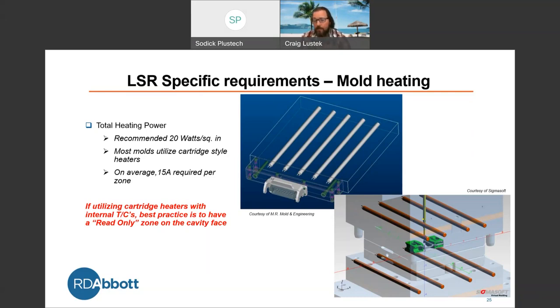A lot of the newer heaters out there, something to watch for, they have internal thermocouples, which are nice, but as soon as you turn the mold heaters on, within anywhere from 5 to 15 minutes, it'll tell you your mold's up to temp. I always like to have a read-only zone added in the face. Sometimes it can't be done, but if you're able to, I recommend asking for that. That way you can actually see what your cavity face is. We want to make sure that your cavity face is as close to your set point as possible. So you're making sure if you're asking for 300 degrees Fahrenheit, we're within that 5 to 7 degree range on that cavity set.